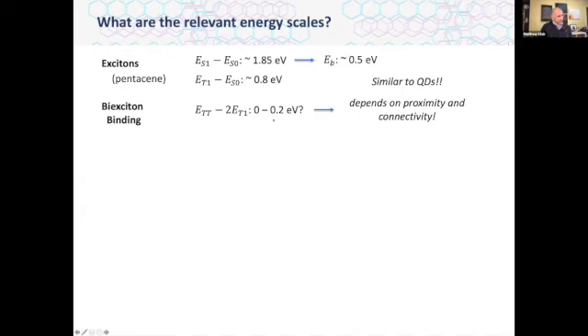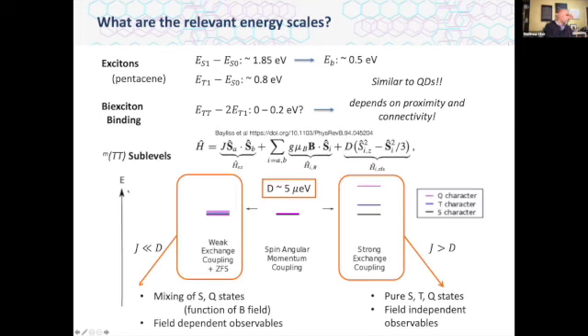But in calculations, people have come up with differences between twice the isolated triplet compared to the bound triplet of something like 100-ish meV. Again, very similar to what we see in quantum dots, which is a point I'll come back to. But what about these sublevels? We talked about, or at least I told you, that spin is essential in determining the recombination. And so if we think about these three states with different net magnetization, what is the splitting between them?